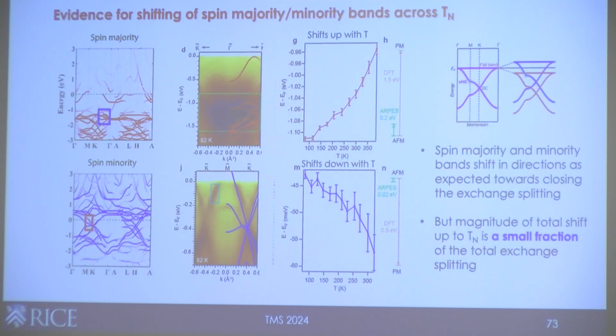And so we can track this as a function of temperature. We can find pieces of the momentum space where we can track the spin majority states, and pieces where we can track the spin minority states. As a function of temperature, indeed, the red bands shift up as expected, and the blue bands shift down as expected, right? This picture is qualitatively correct. But if you look at the energy axis, you realize that the amount that they shift is, in this case, 20 millivolts, in this case, 200 millivolts, and that's compared directly to the exchange splitting expected from DFT. You can see that the amount of shift we actually see going across the ordering temperature is very small compared to the total exchange splitting expected.